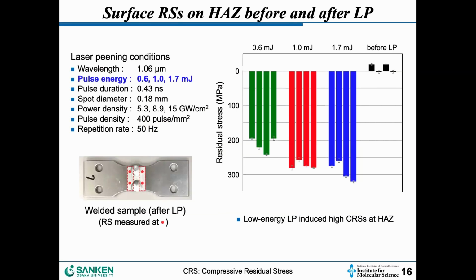And this is the typical result of the residual stress measurement for one welded sample. Again, the same parameters. We measure four points like this, shown by that one, and we compare the result like this. By increasing the pulse energy, we can get higher compression on the surface. However, 1.0 millijoule is enough if you compare to the tensile strength of the material.